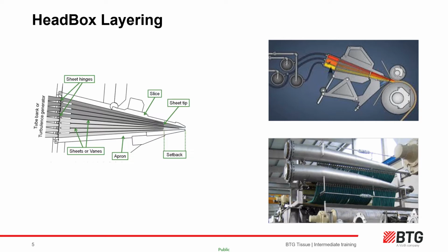Here we see the internal drawing of a similar headbox, but with 2 and not 3 layers. A tube bank from a tapered distribution pipe maintains an even CD flow, hence even CD fibre distribution and weight profile. To maintain laminar flow and to keep the fibres apart, there are a series of hinged polycarbonate or Lexan sheets in the headbox, which taper towards the outlet of the headbox or slice. The stock is fired under pressure from the adjustable slice lip between the felt and/or the forming fabric or wire, which wrap the forming and breast rolls respectively.